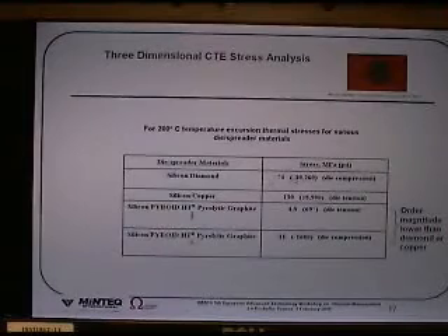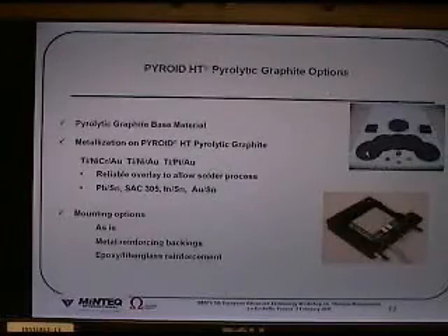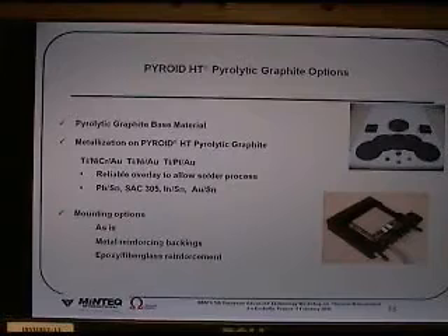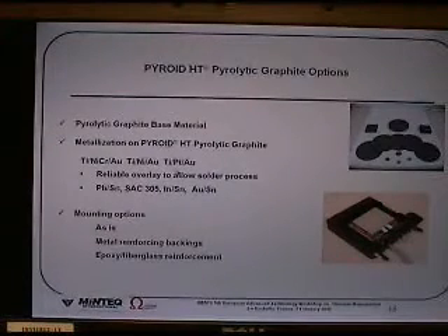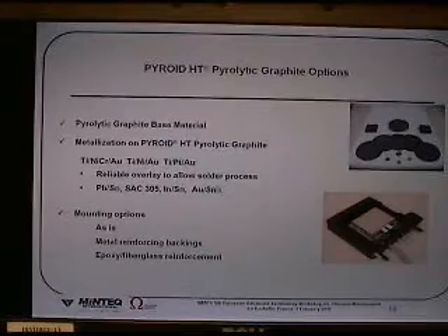If we look at the die spreader material stress results, what you find is that for pyrolytic graphite in silicon with Pyroid HT, you have an order of magnitude lower stress than that which is experienced between diamond and silicon. This presents a number of options for the utilization of pyrolytic graphite, Pyroid HT, in these applications. We can use it as a base material. We can metallize the surface, either a single surface or all surfaces, with a wide array of metallization schemes. We can solder it using a wider range of solders that are commonly used. We can mount it as is if you use a mechanical device, or with the metal reinforced backing, or most recently, we've also developed an epoxy fiberglass reinforcement technique.